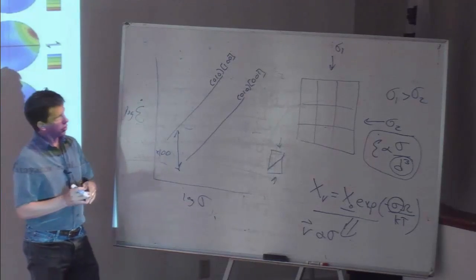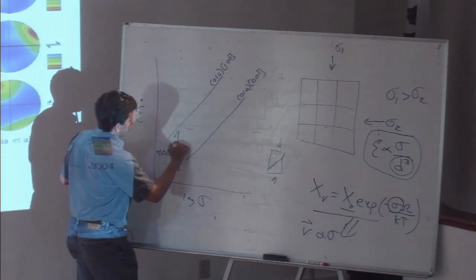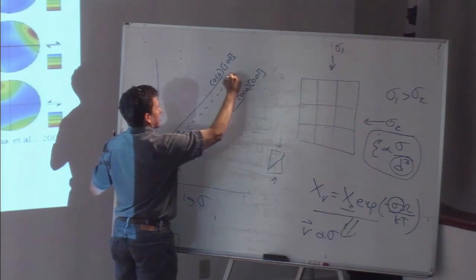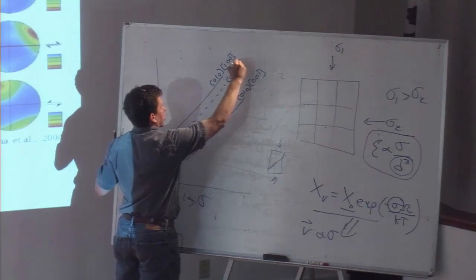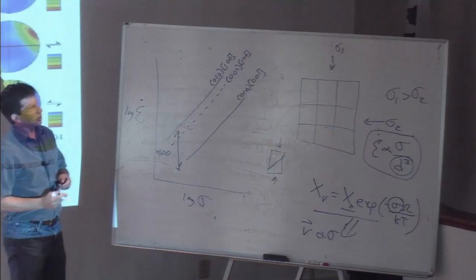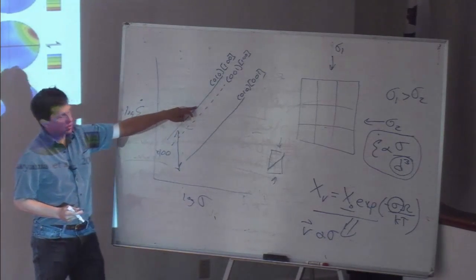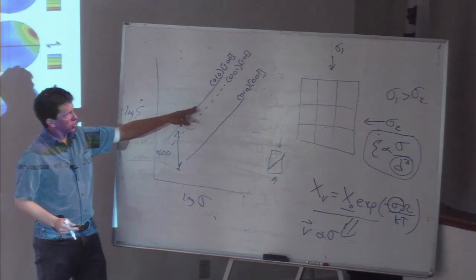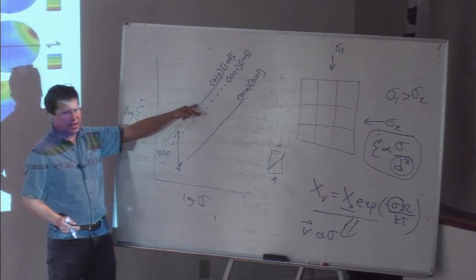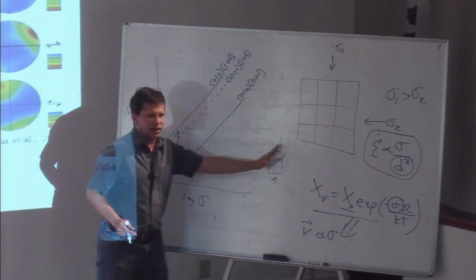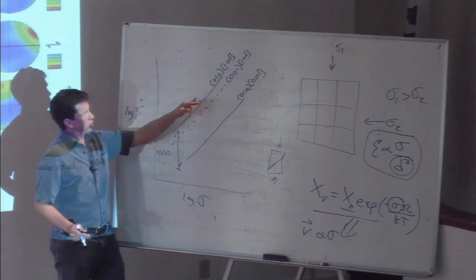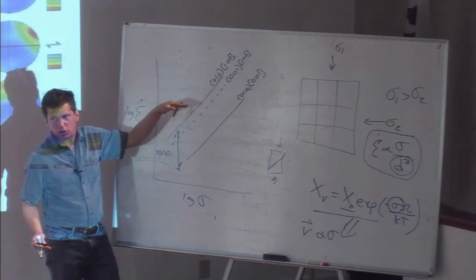Olivine is orthorhombic, and so the other major direction, I'm going to just dash it in here, is deformation on the C plane in the 100 direction. And if you spend too much time doing this, you start to get confused, but that's not a big deal for right now. So this is the easiest direction, and so the crystals deform fastest when they're aligned like that, and those crystals rotate the fastest and align into the flow field, and that's why the LPO is dominated by this at dry conditions.